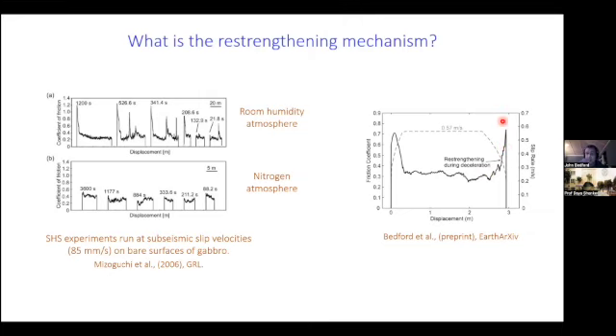And potentially, in terms of thinking about rupture mechanics, if we're getting very fast healing mechanisms operating along faults just after they start to decelerate a little bit, this is the sort of thing that maybe could be happening during a pulse-like rupture on natural faults, where you need fast healing mechanisms directly behind the rupture front to re-strengthen the fault and stop it slipping again as it's reloaded from the energy that's been imparted on it from elsewhere in the fault.